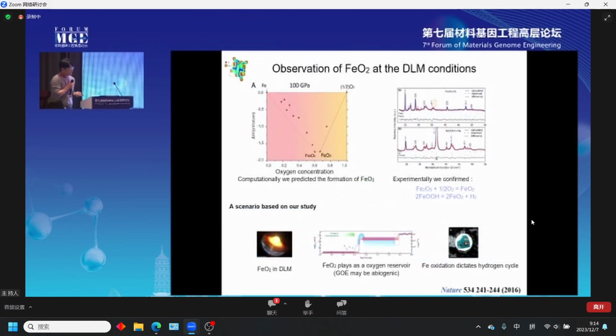So this was the first paper we published a long time ago, and at that time it was quite shocking, because people believed that hematite, Fe2O3, with an iron to oxygen ratio of 1 to 1.5, was the most oxidized form of iron oxide. But under pressure, we predicted that at 100 gigapascals FeO2 can exist, and experimentally it was very easily synthesized. Based on this structure prediction, we tried to explain that 100 gigapascals corresponds to the deep lower mantle, which can be much more oxidized in terms of oxygen concentration.